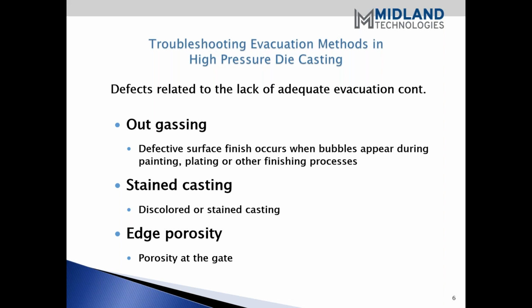Edge porosity is gas trapped at the point of the gate. It can occur around the periphery of the casting in different locations, but it's mostly associated with temperatures and or the cavity fill time. So again, we can minimize that by having proper evacuation.